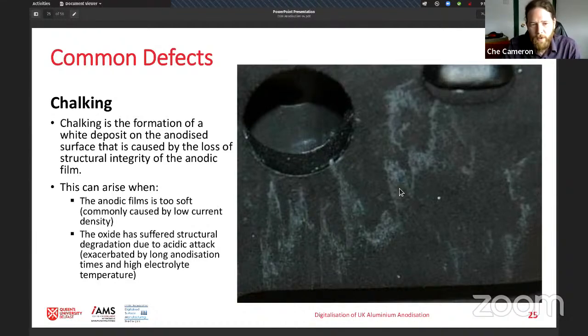And that can happen when films are too soft, which could be not enough current density. And you may notice then we can have burning if the current density is too high, chalking if the current density is too low. So it's clear that if you're undertaking a process like this, there is some envelope that you must stay within to get a proper result. And chalking can also happen if you have a very long dwell time because the acid has been attacking that oxide the whole time, weakening it.